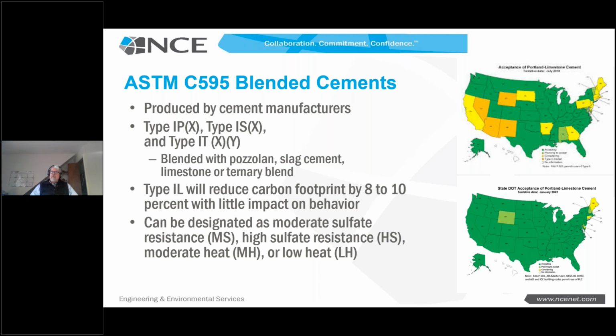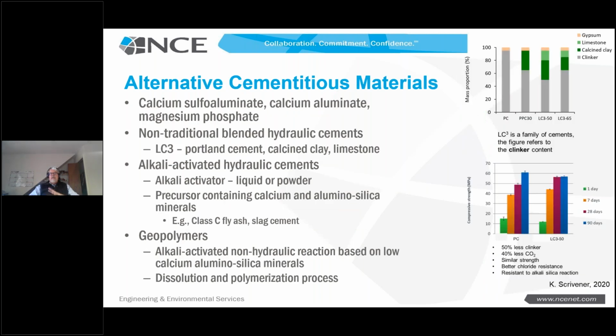And so if you can work with a ternary blend of a limestone with a pozzolan or a slag, these can be very effective because the sulfate balance can be handled by the cement supplier, and we can have a very workable product. There's also a lot of interest, because clinker is so energy intensive and so carbon intensive, to look at alternative cementitious materials.